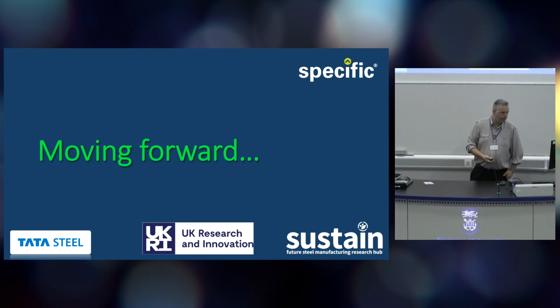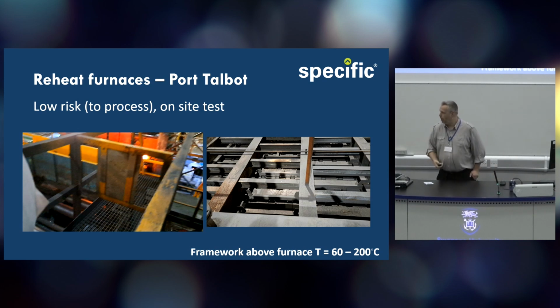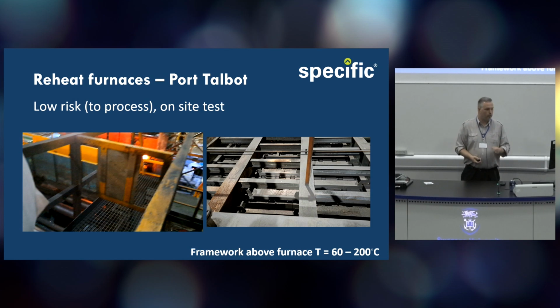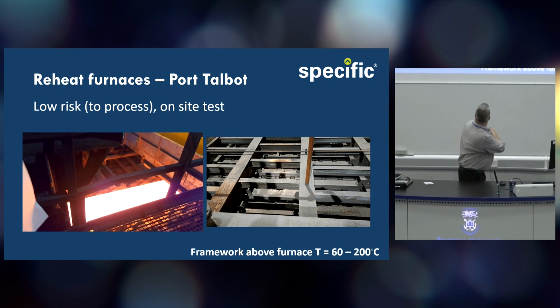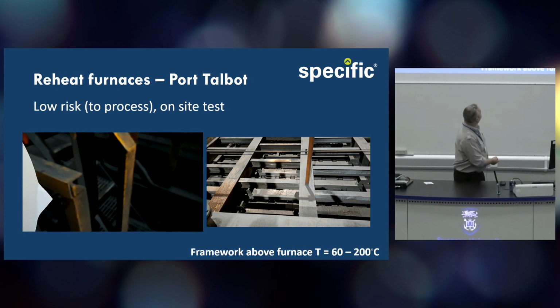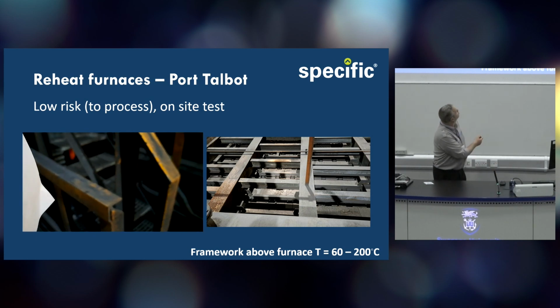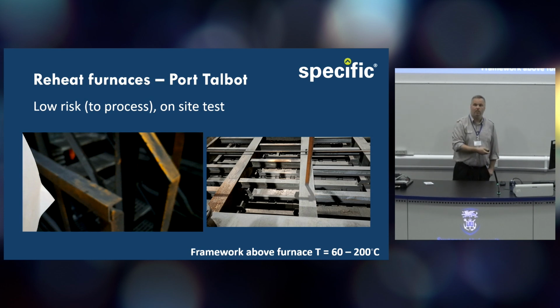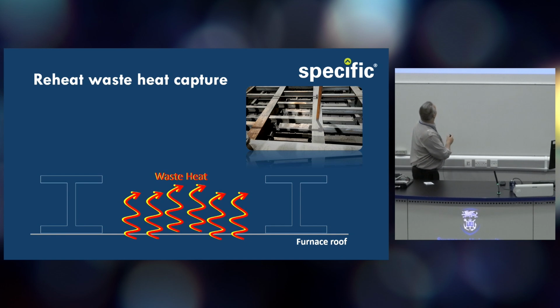So moving forward, through our interactions with Sustain, we were put in contact with the hot mill at Port Talbot, and we have a lovely process there where we've got a cast slab going through into the reheat furnaces. And then this photo on the right hand side is actually the furnace oven top. So there's a series of stanchions above there, a series of I-beams, and then temperatures in this region around here can be from 60 degrees centigrade to around about 200 degrees centigrade. So essentially what we have is a lot of waste heat coming through the roof of the furnace, and what we're looking to do is actually find a way to capture that.